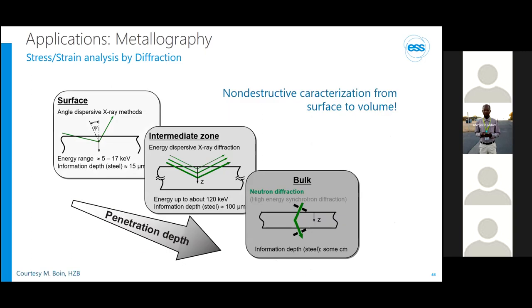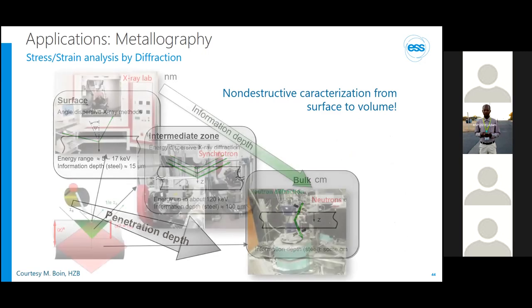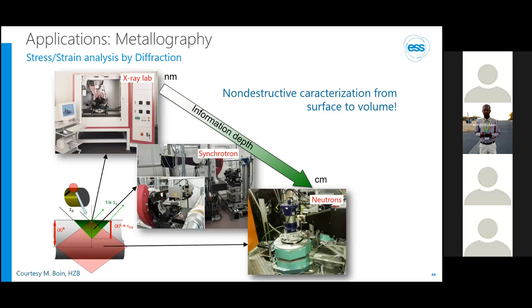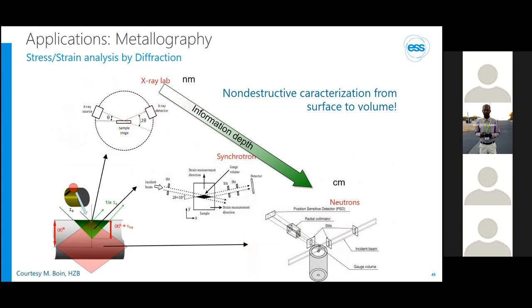And this can be done by X-ray diffraction, of course, as well. And here again, when using neutrons for this, it's very useful if you want to investigate the bulk structure of materials. And you can see it done in practice. It's the same technique done with lab X-ray, synchrotron X-rays, and neutrons. And what it also means in practice is that you have different gauge volumes. So the volume you're actually probing is different in size